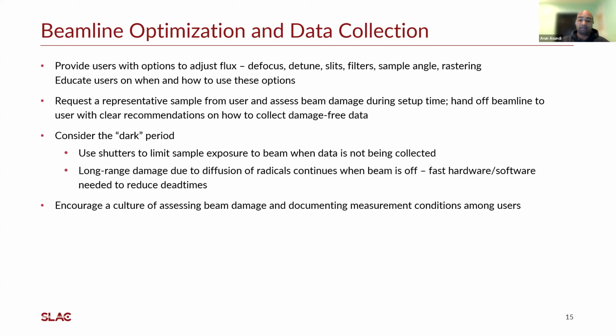Yeah, I think that for measurements, especially if it's a sample that's going to be used multiple times for different types of measurements, this is something that should be considered from the very start. So, for instance, in your question about iron and sulfur, it would be best to start with the measurement that has the lowest chance of beam damage. So that's probably iron in the hard X-ray regime.